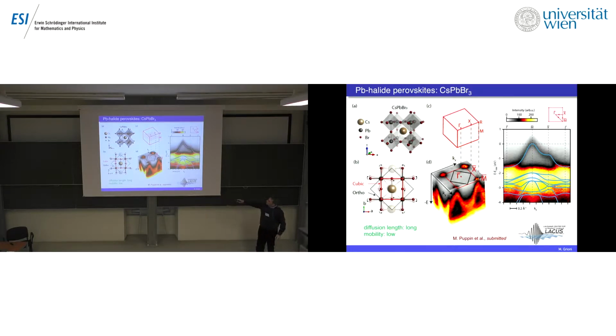This is an overview. I should say this material at high temperature is cubic. At room temperature, it's actually orthorhombic, almost tetragonal. So what is plotted here, the red square is the projection of the cubic Brillouin zone. The black square is a projection on the surface of the orthorhombic Brillouin zone. Now, in this representation, Kx, Ky, energy, you see that there is a band with the bottom at the gamma point, which disperses up and has maxima at the corner of the cubic Brillouin zone, these the endpoints. In fact, in the orthorhombic system, you should see a replica of this maxima here at the gamma point, because gamma is equivalent to M in the orthorhombic.